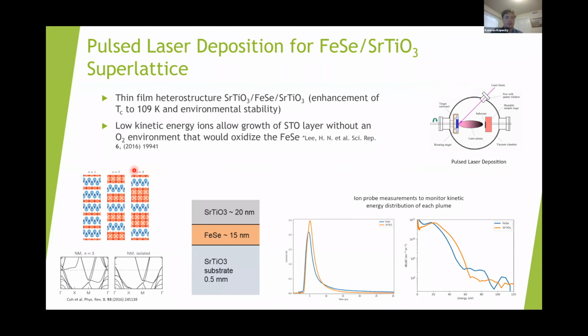So our main goal with this project was to grow an iron selenide and strontium titanate superlattice. Iron selenide has been shown to be a high temperature superconductor under high vacuum. The detriment of iron selenide, though, is that it easily oxidizes in atmospheric conditions. And so it is proposed to layer the iron selenide with strontium titanate in order to prevent this oxidation, as well as enhance the superconductivity of the film. And this is through proposed electron doping and electron phonon coupling.